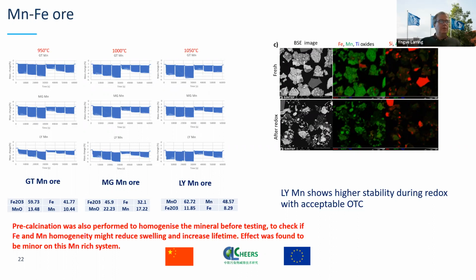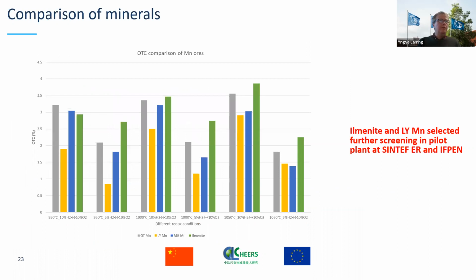So this was tested further as well. We did a pre-calcination to homogenize it because, as you can see on some of the fresh samples, the iron and manganese are in different places, so we wanted to homogenize a little bit and also react with other species in the sample to make it more homogeneous. Even though from this slide it's not easy to see which one we should select, based on several criteria, the ilmenite with a good oxygen transfer capacity and the manganese ore with a little bit less oxygen transfer capacity were selected, also based on the lifetime of these materials and how they looked after the initial test.